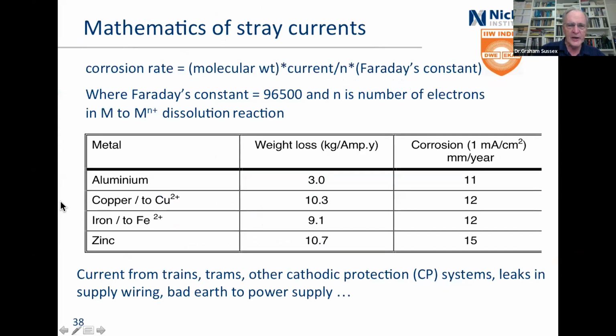These are the mathematics, stray currents. If you're talking about aluminium, 1 milliamp per centimetre squared, you get this number of millimetres per year. If you're talking about copper, you get about that, iron about that, and zinc about that. So stray currents can make things corrode very rapidly. And they're reasonably easy to pick that it is stray current, but the cause of it may be quite difficult. It may be that there's problems with earthing of the electrical systems after faults in a building, or it may be that somebody else has got some cathodic protection and it's got done wrong, but that usually is reasonably well controlled. As I say, leaks in supply wiring, bad earth.